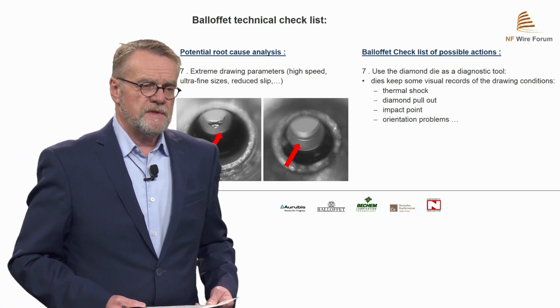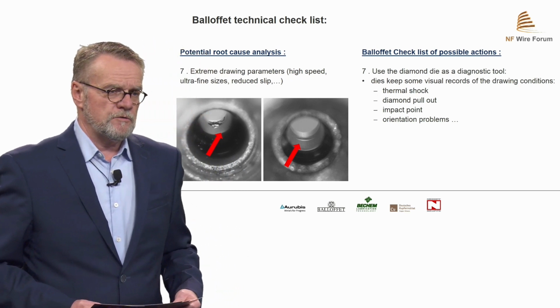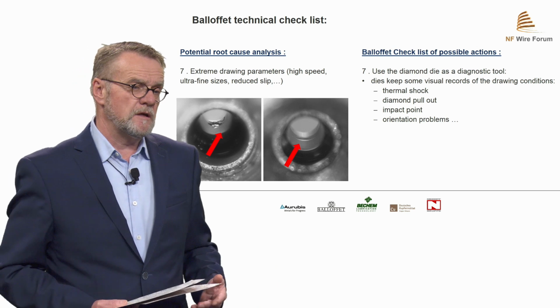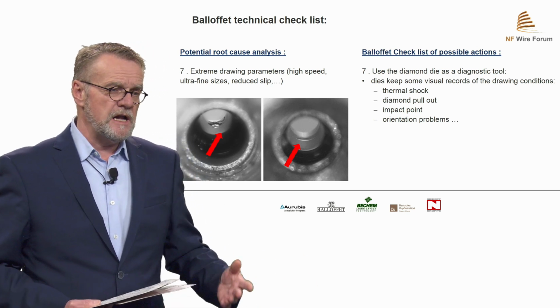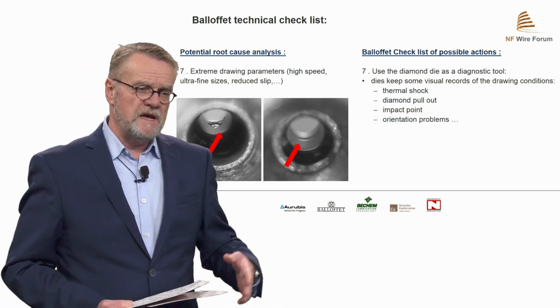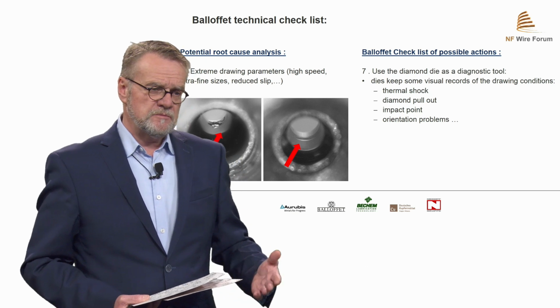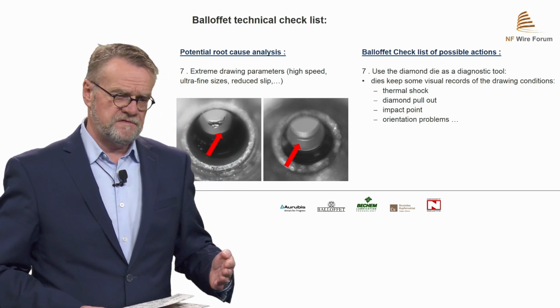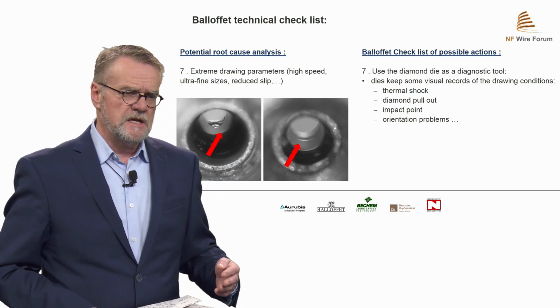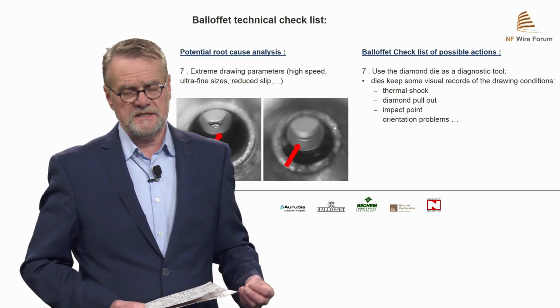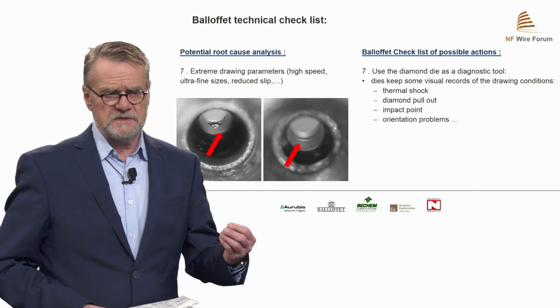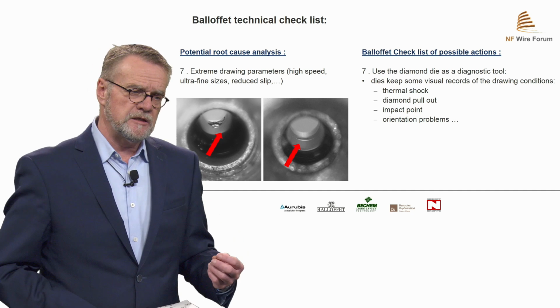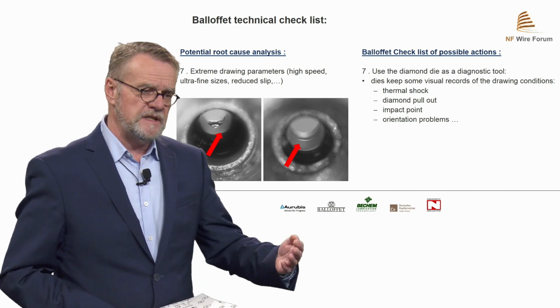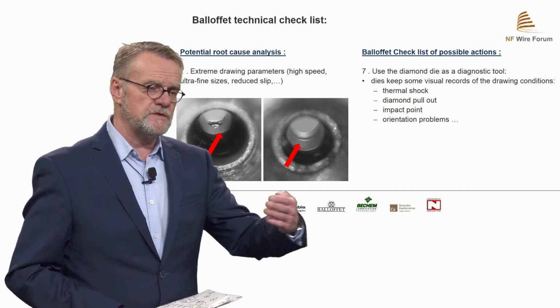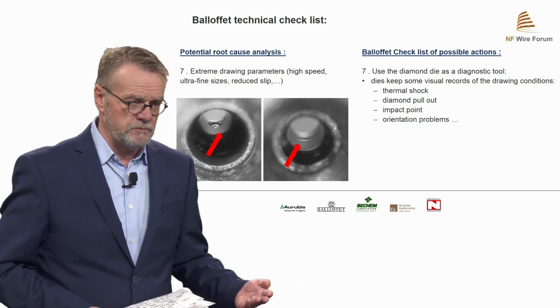And also the extreme drawing parameters, because we are using high speed, we have ultra-fine wires, we have a reduced slip. That means our dies have to be perfect, absolutely perfect. We have to check if there is a drawing ring inside, because in a drawing ring material is sticking, and we take this material into the next die and we create problems.